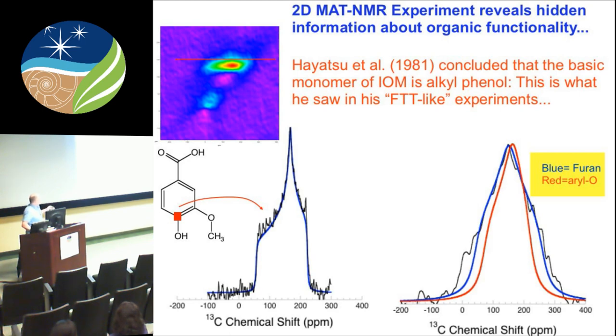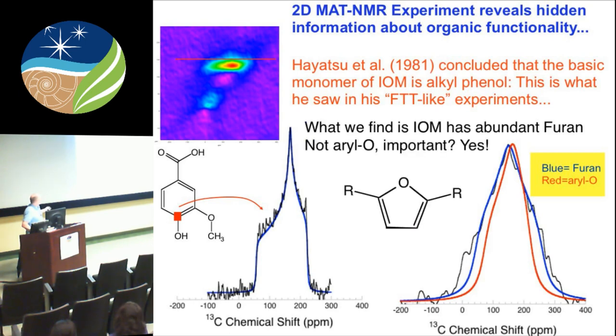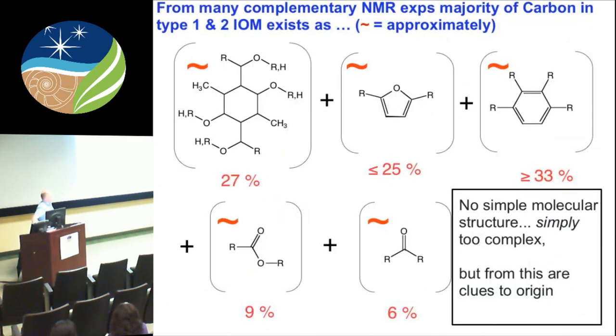And while it might seem like a trivial difference to you, it turns out it's actually very significant. What we found is that IOM does not have a lot of alkyl phenol, and I can explain to you later why Ryo made the mistake he did. But in fact, it has a lot of a somewhat related electronic group called furan, and it turns out that was critically important.